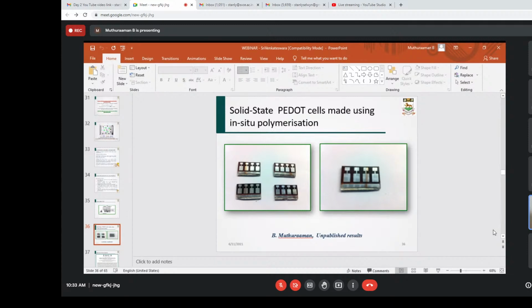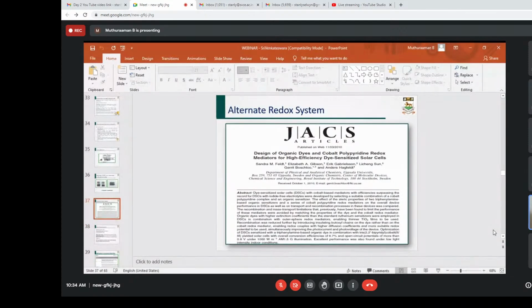You can see in this one, both the anode and the cathode in a single plate. The long strip below is the cathode, and the small strip above is the anode. So this is the mechanism. This geometry we made for the first time, but the efficiency is 4.5% and the stability is very low. It doesn't even last for a day, so it's highly unstable.